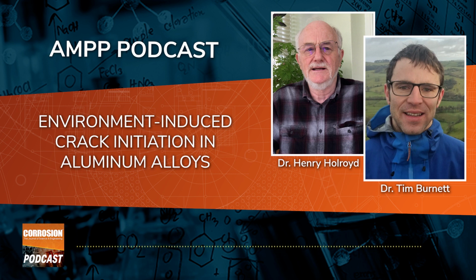I think some of the really valuable things that we've learned recently is that there are clearly different stages of initiation, in terms of that very initial nucleation of a crack, but then actually the short crack behavior or small crack behavior, where the crack is smaller than a grain of the material, and then when the crack is longer it actually has a different behavior. Just us understanding that better is, again, a new opportunity to investigate and potentially interrupt some of these processes.